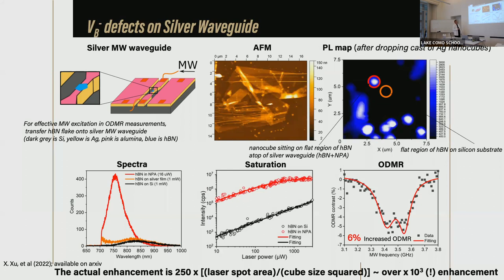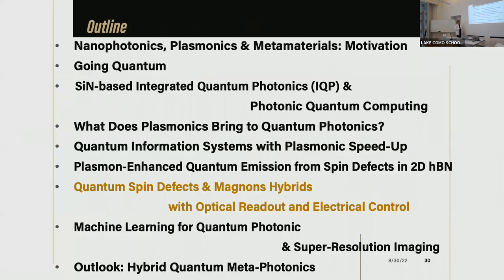So we have increased it as much as 250, but if you take into account that the size of the cube is so much smaller than the size of a laser beam, the enhancement provided by the cube itself is way over 1,000. And for 2D materials, it's quite spectacularly high enhancement. And we do obtain indeed this spin contrast, which is needed for many sensing applications.